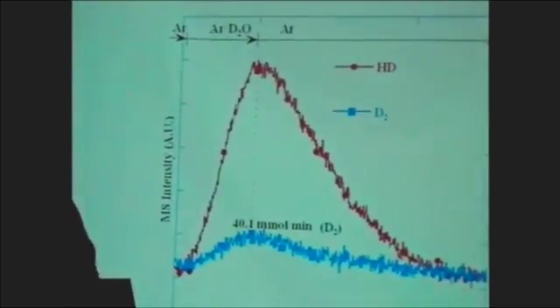So finally we were able to do a material balance to show it's possible to do the reforming of the coal by using this nickel manganese catalyst. And this nickel manganese catalyst is a coprecipitated catalyst here. It's very stable. The particle size does not grow during the reforming reaction simply because this nickel particle is locked in with the manganese and sodium carbonate together. And sodium carbonate is known as a very good catalyst for coal gasification. So by luck, this catalyst happened to become a very good catalyst for coal gasification.